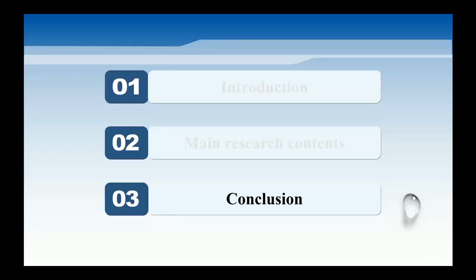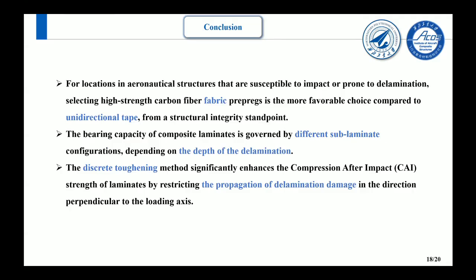Based on the investigation detailed above, the primary conclusions are as follows. To start with, for locations in aeronautical structures that are susceptible to impact or prone to delamination, selecting high strength carbon fiber fabric prepregs is the more favorable choice compared to unidirectional tape from a structural integrity standpoint. Additionally, the bearing capacity of composite laminates is governed by different sublaminate configurations depending on the depth of the delamination. Last but not least, the discrete toughening method significantly enhances the compression after impact strength of laminates by restricting the propagation of delamination damage in the direction perpendicular to the loading axis.